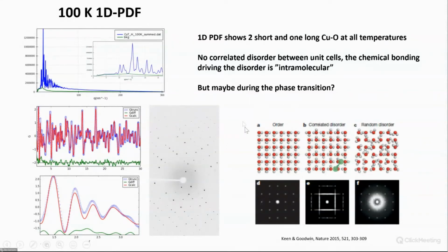So if we look at this famous review by Dave Keen and Andrew Goodwin, where they put this example of a water crystal: if we have perfect order, we have the Bragg diffraction. But if we now invoke hydrogen bonding, there will be some local structure correlation that will give diffuse scattering. And of course, if these water molecules just don't feel each other, then we have diffuse scattering going out here. So this is the example of copper Tutton salt. Basically, we have no correlated disorder between the unit cells. The chemical bonding that's driving this Jahn-Teller distortion is, you can say, intramolecular.